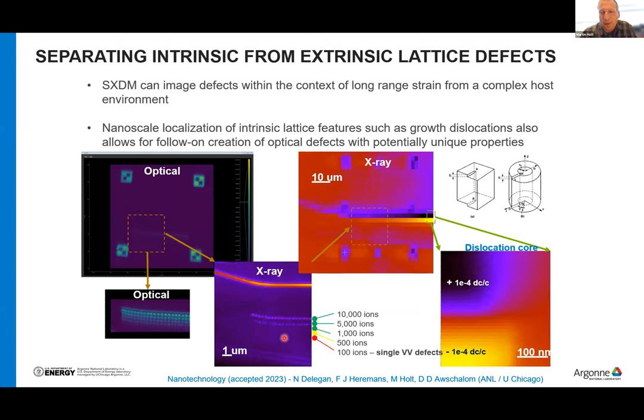We can try to get down to this level, I think, with the upgrade. We'll see how that goes. But then your question is, hey, what is this extremely large thing blowing through my scanning area? And that is actually the tail of a slip dislocation that has a dislocation core within silicon carbide.